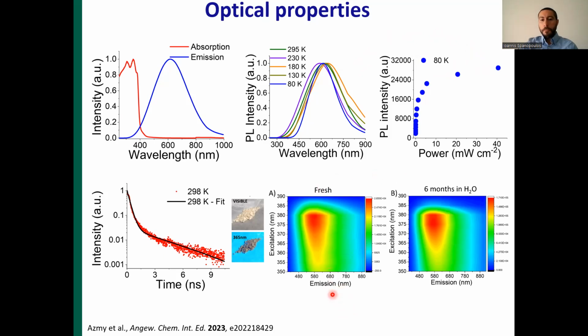In order to evaluate whether the optical properties deteriorate upon water adsorption or water treatment, we recorded the PLE, the photoluminescence excitation spectra, for the pristine material and the water-treated one. And apparently there is no difference in the PL peak position and the PL bandwidth after 6 months in liquid water, which is a clear demonstration that porosity not only rendered the material porous, but also didn't affect the optical properties. And the optical properties were maintained even after 6 months in liquid water.